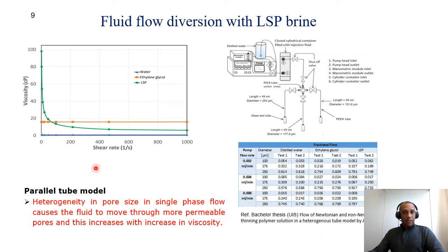So we took a dive into polymer flooding experiments. We started by preparing a polymer with a concentration of approximately 1000 ppm in a brine of 1000 ppm sodium chloride. What we observed was that the viscosity at low shear rates was relatively high, but as we increased the shear rate, it decreased. This is a typical rheological behavior for a polymer.